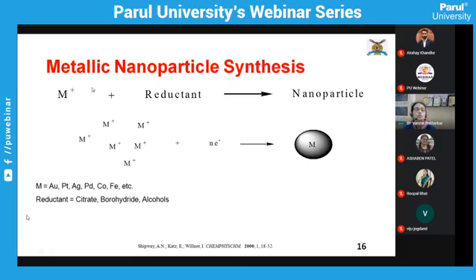and therefore this is something which can be of real interest. So the chemistry is that you have a metal electrophile, which, with the help of a reducing agent that can transfer its electrons to the electrophile, leads to the formation of a neutral metal particle in the form of a nanoscale particle, or a nanoparticle. The metals can range from gold, platinum, silver, palladium, cobalt, iron, anything it can be, and the reducing agent could be citrate, borohydride, alcohols, or any other reducing agent typically. There is no rocket science here, it is simple chemistry that is involved.